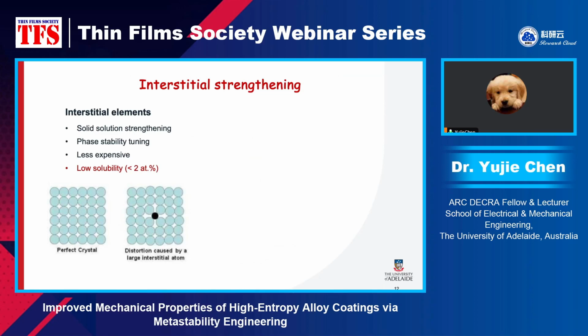So it comes to a question, because if we can only add less than 2 atomic percent interstitial elements, it will not help us to reduce the cost. And also, if we want to enhance the solid solution strengthening and tune the phase stability, we may need to increase the amount of interstitial elements. Then it comes to a question: is there a way that we can dissolve a high concentration of interstitial elements in high entropy alloy without the formation of brittle ceramics? The answer is yes. Magnetron sputtering can do it.